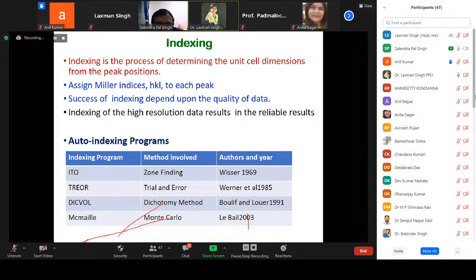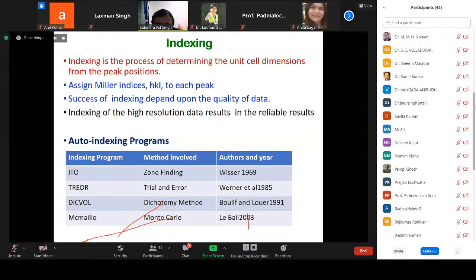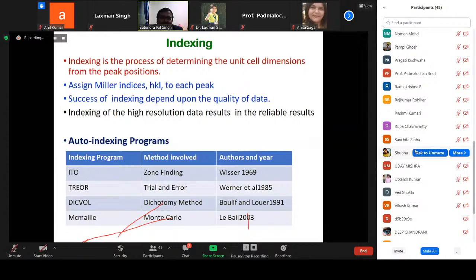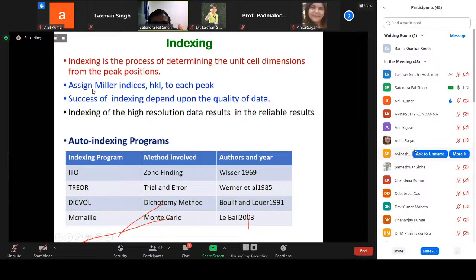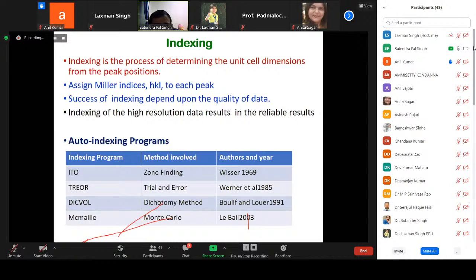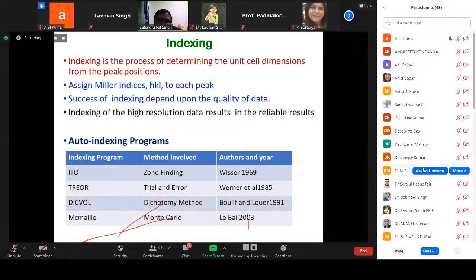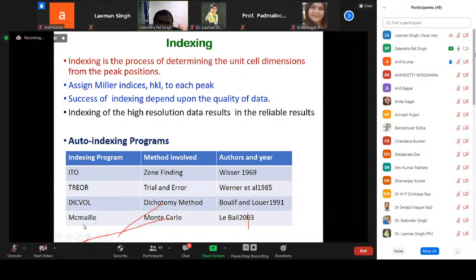So, indexing is the most difficult process for unknown systems. When you are able to overcome this indexing process, then things will smoothly follow. In the indexing process, you assign the hkl plane to each of the diffraction peaks, and then find the unit cell, the unit cell parameters and the crystal system. Manually, sometimes it becomes hard to index a system. Then there are several auto-indexing programs. They are ITO, Treor, Dicvol, and McMaille.